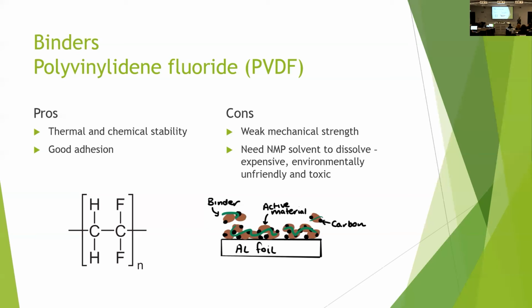So it doesn't really add to your capacity in the battery, which isn't really good. And another really big negative thing about PVDF is that it needs an NMP solvent to dissolve it when you are making the slurry. And NMP is really expensive, it's harmful to the environment and harmful to your health. And so really careful handling is needed of this solvent.